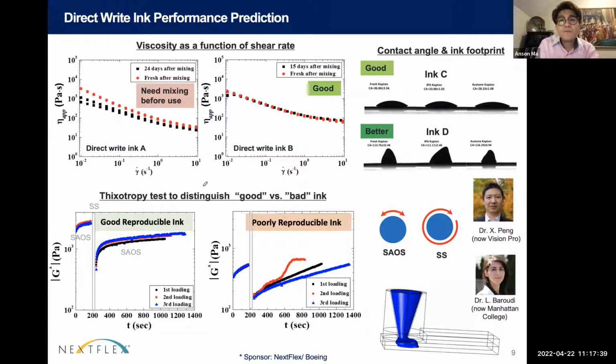Unfortunately, certain inks, because of the use of metallic particles and so on, tend to settle, and depending on how well you formulate them, they may aggregate and settle, right? So one trick that you can do is run a rheology test. For example, what we call a flow curve here. You can measure the apparent viscosity as a function of shear rate. You can also check over time whether there's a deviation in the viscosity profile. For example, if the particles start settling, then every time you sample from the top, you can see the viscosity drift over time, and it becomes less and less viscous just because the particles are settling and you're collecting the sample from the top.